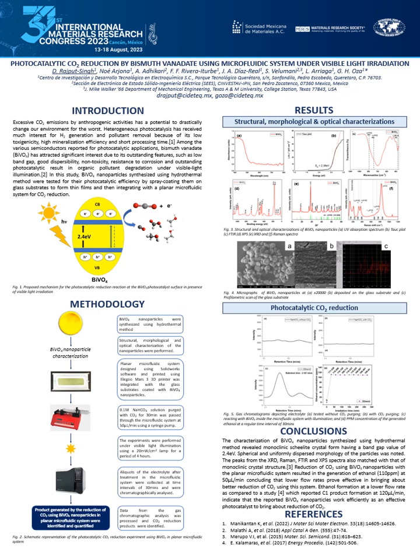Also, the nanoparticles were characterized morphologically using SEM and EDAX, and from the micrograph, it can be seen that the nanoparticles were in the form of monodispersed, spherical, ovoid nanoparticles. The nanoparticles deposited onto the glass substrates were also analyzed using SEM, and the micrograph showed uniform distribution and a uniform coat of the nanoparticles on the surface of the glass slide.